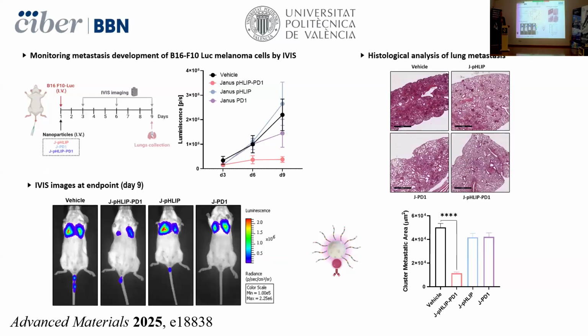The system works in vitro. I will show you just some slides, but it also works in vivo. This is a quite simple model, a metastatic model in mice. We inject melanoma cells that express luciferase. The cells go to the lungs and start to make metastasis, and you can follow the metastasis because the luminescence grows with time. The same happens with some control nanoparticles, but if we add the complete nanoparticle that was designed, there is a reduction. You can also see in the histological analysis a clear reduction of the metastatic clusters.